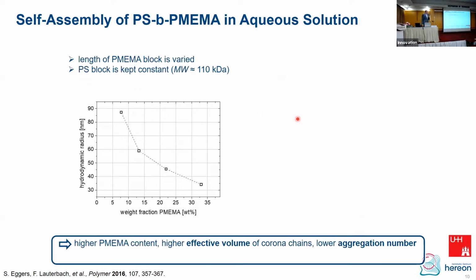Now, when we do dynamic light scattering and study the size of these micelles in solution, here you see something interesting, because what is plotted here is the hydrodynamic radius as a function of the amount of the hydrophilic block, the stimuli-responsive hydrophilic block. And the polystyrene is always the same. So we keep polystyrene similar and just increase the length of this hydrophilic block. And what you see, the longer the block, the smaller is the hydrodynamic radius. At first you would expect the opposite. Longer chain means larger structure, but you see the opposite.